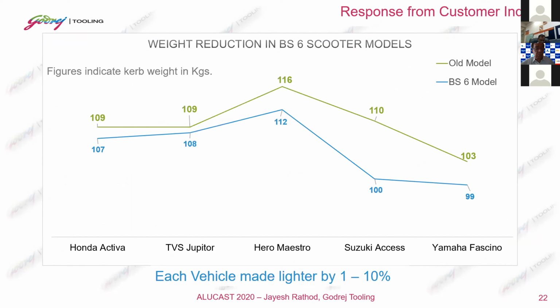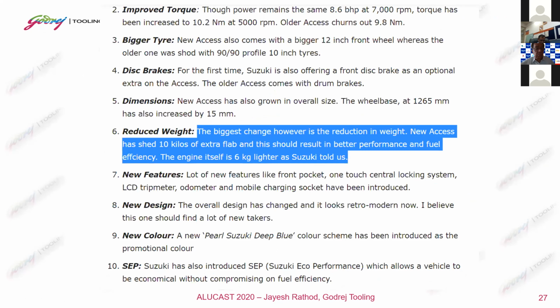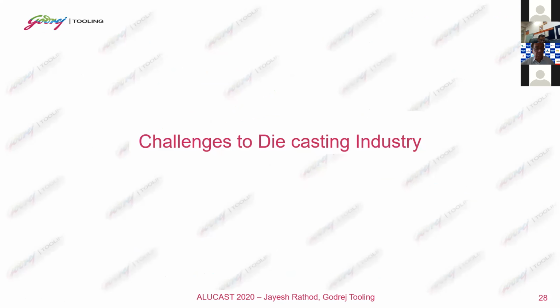If we look at what is happening in our country, I tried to track Honda, TVS and Hero. What was the difference between old models and BS6 models? We can see that weight reduction in the range of 1 to 10% has been done by all the two-wheeler OEMs, and more aggressively by Suzuki. 10 kg of extra weight has been removed, and that has come through making the engines lighter by 6 kg. It's a huge tall order to reduce the engine weight by 6 kg. Based on this, these actually form the challenges to the die casting industry.